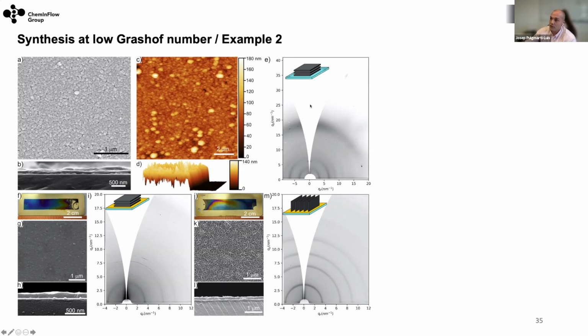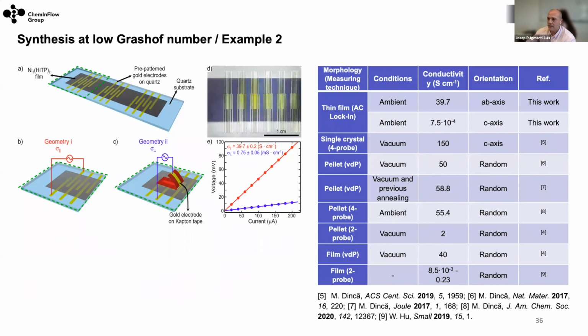We also use different surfaces. We did it in glass, in quartz, in gold. So they all work. But what was also very interesting in our approach is that now we could do measurements also through the film. So we could measure in plane and out of plane.